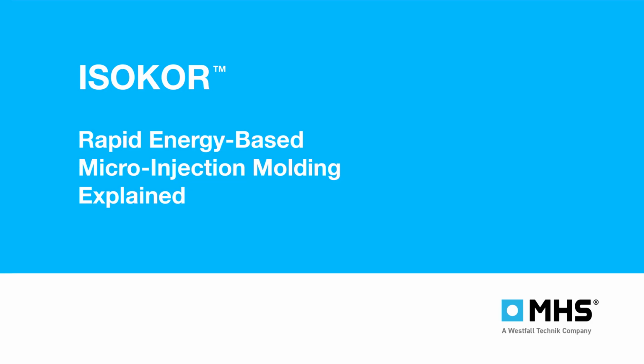The valve gate at the mold suddenly opens. Because the pressure in the empty microscopic cavity is basically zero, the highly compressed melt instantly expands into the void to equalize the pressure. Oh, man. We aren't actively pushing it with a stroke. The stored energy is causing it to practically explode into the mold in a matter of milliseconds. Milliseconds, that is fast. And crucially, while this explosive expansion is happening, that MDU plunger is simultaneously inching forward just enough to instantly reestablish the pressure drop. It maintains that high plateau. Finally, the valve pin slams shut.